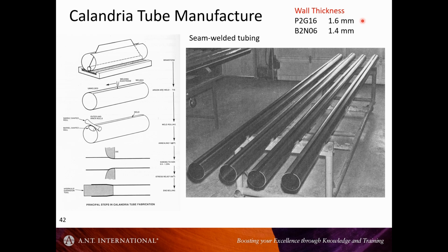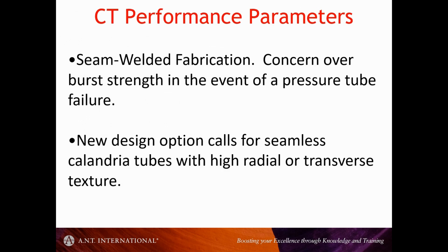These things happen in reactor development, and particularly in the CANDU reactor, because neutron economy is so important, because they only run on natural uranium. And that was one of the outcomes, that the calandria tube failed on the LOCA. So there was a program initiated at that time, a lot of concerns about welded tubes. So the program was initiated to make a seamless calandria tube, and we could get away from the weld.